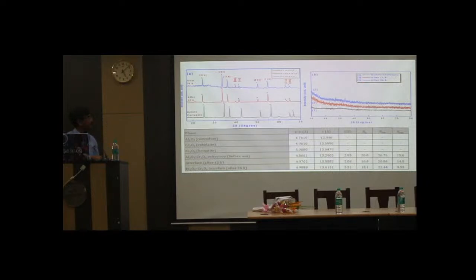So you see this is the 0 unreacted refractory, and then after 12 hours, after 36 hours, and you cannot find any crystalline phase in the glassy part. So whatever aluminum is coming from the alumina chrome, it reacts with the glassy phase and enters into the glassy structure. You cannot see any corundum or any other phases there.